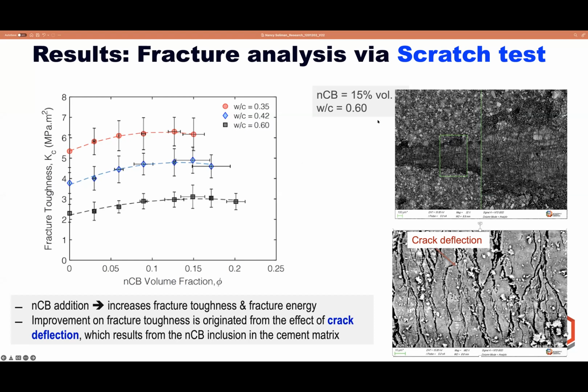To confirm our result, we used the scanning electron microscope, where we observed the fracture mechanism in an image of the scratch groove in the mixture prepared with water cement ratio 0.6 and nanocarbon black 15%. What we observed under the scanning electron microscope is that the tortuous, non-planar geometry of the crack was clearly visible on the crack surface, which proves that this enhancement of the fracture toughness results from crack deflection.